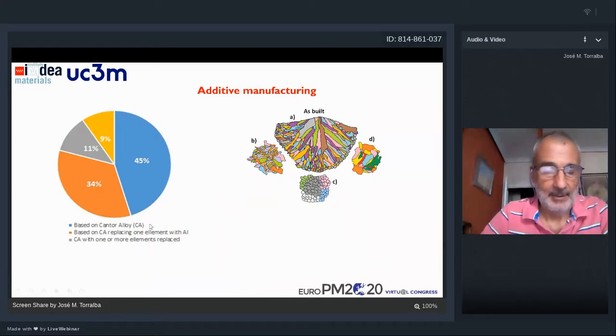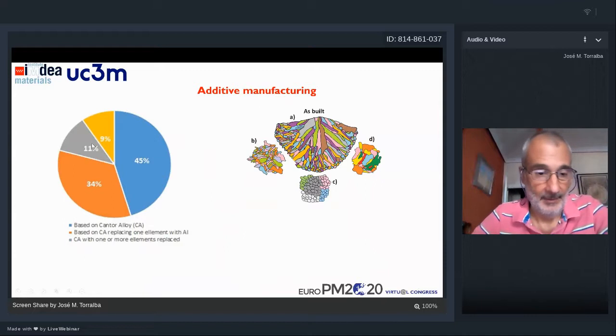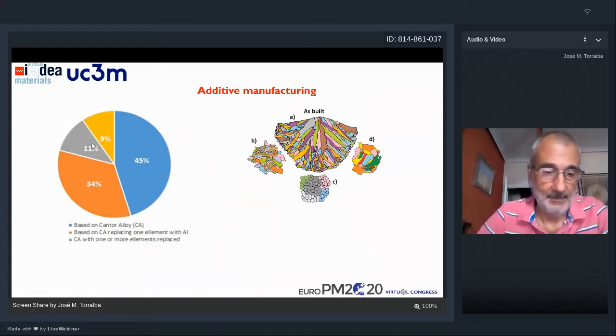The Cantor alloy, I mentioned before, and there is in the order of 34% of papers in which we have replaced the Cantor alloy by aluminum in order to tailor the microstructure. And we have also some refractory metals, and we have also some other alloying elements. But most of the works are based on the Cantor alloy.